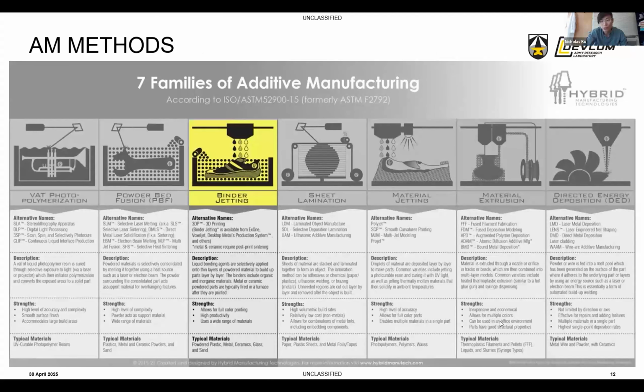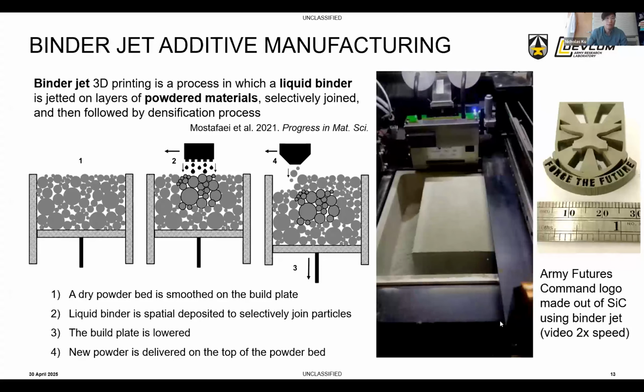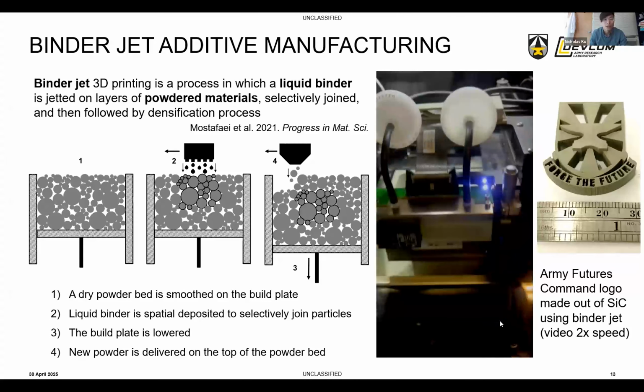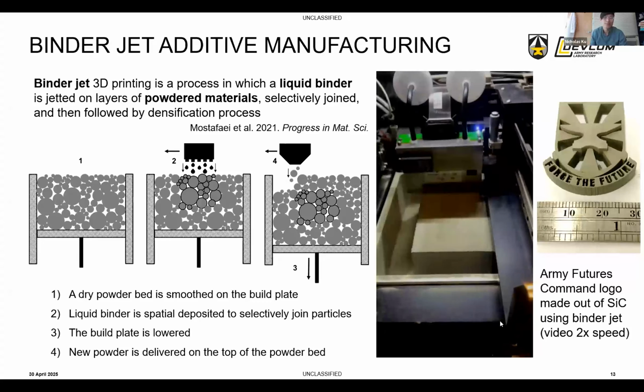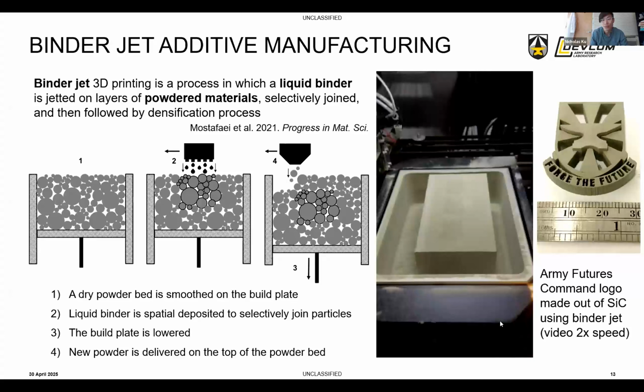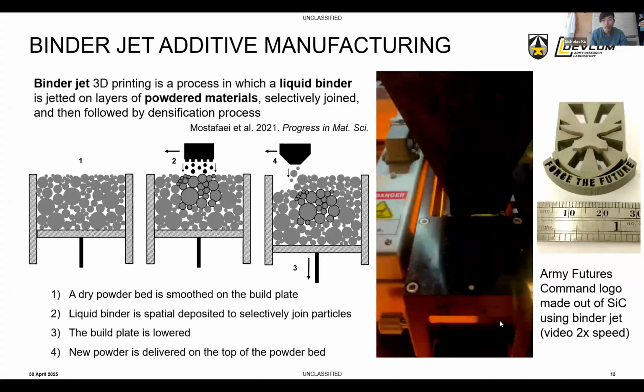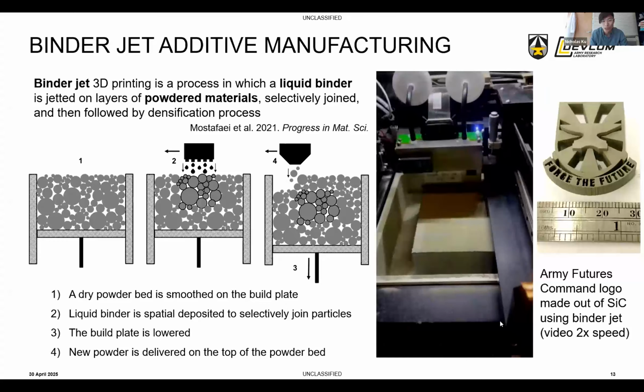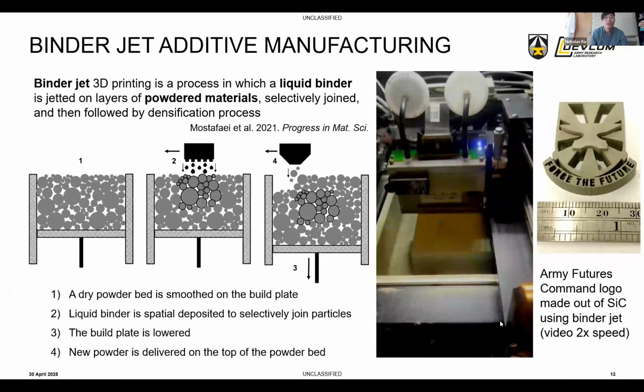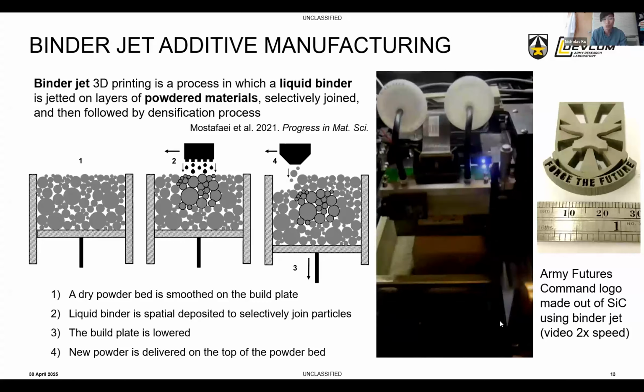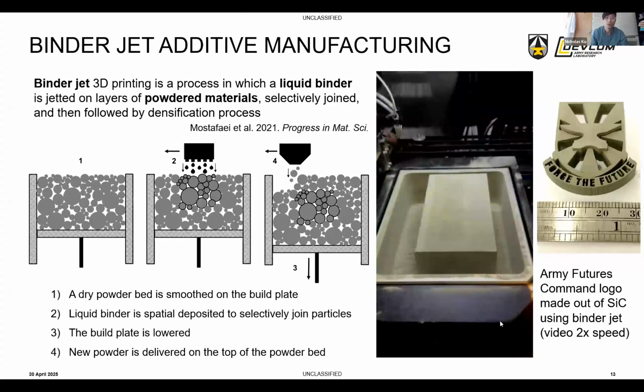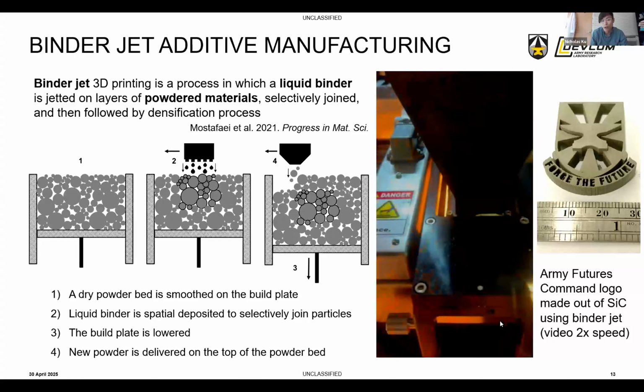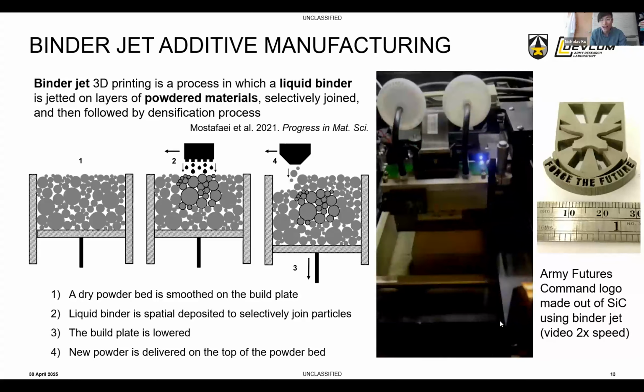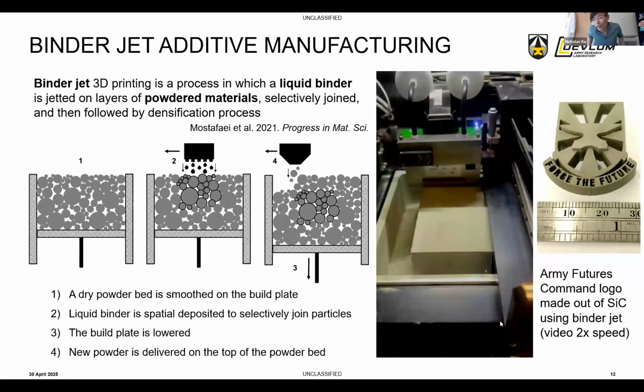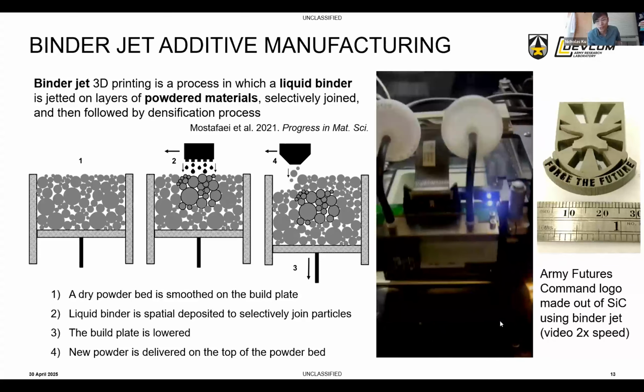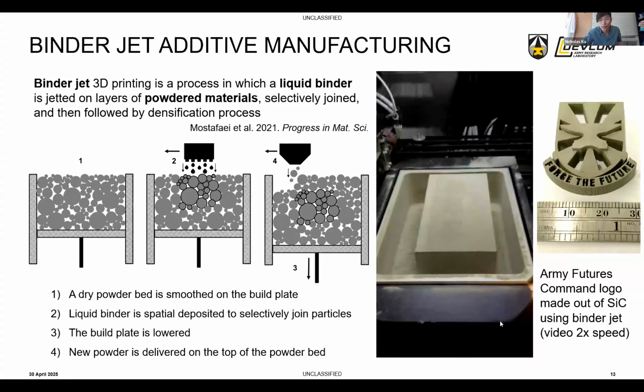Changing topics from material extrusion to binder jetting. Binder jetting is an additive manufacturing technique where you have a dry powder bed. You use a print head, not unlike what's in your copy machine, your Xerox machine, and that drops droplets of liquid binder to locally glue your powder together, and then another layer of dry powder is placed on top. As any good 3D printing research group, we printed our logo. There's the AFC logo on the right-hand side out of silicon carbide.